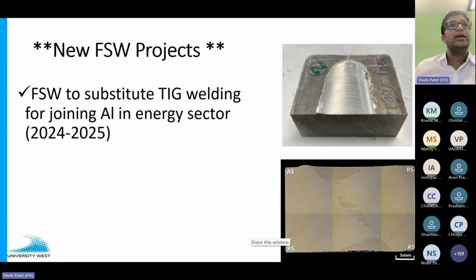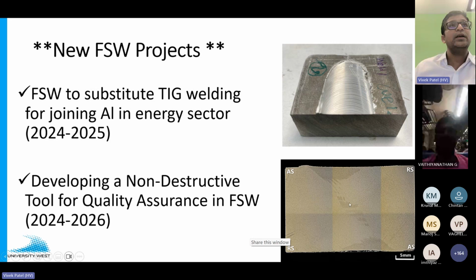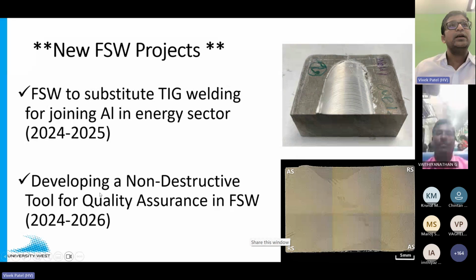Then some new projects. Friction stir welding can be a substitute for TIG welding for several applications in joining of aluminum, especially for energy applications. We have been welding this 25 millimeter thick block, and you can see this 25 millimeter thick block is welded in two directions. One welding pass is on one side, and on the other side there is another welding pass, and we have completely defect-free welds of thick blocks for energy applications.